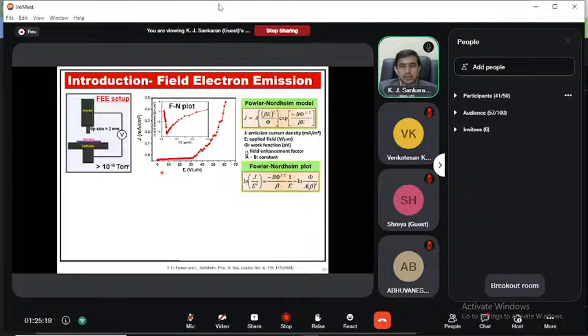So how do we characterize a field electron emission material? There are some parameters: the current density, applied electric field, the turn-on field, the field enhancement factor, and also the work function. These are the parameters which help us evaluate a field electron emission material. There is the Fowler-Nordheim model, developed in 1928 by Fowler and Nordheim. This is the equation for that, and from it they made the plot of ln(J/E squared) to determine the turn-on field as well as the field enhancement factor.